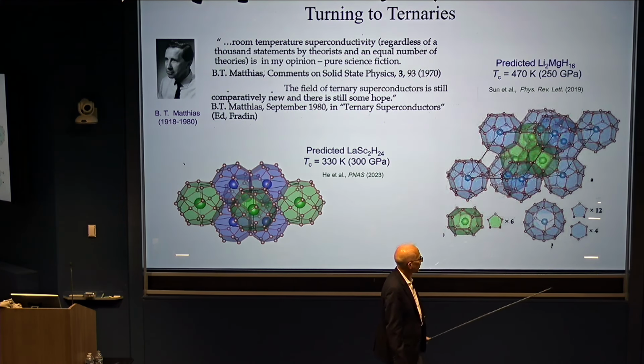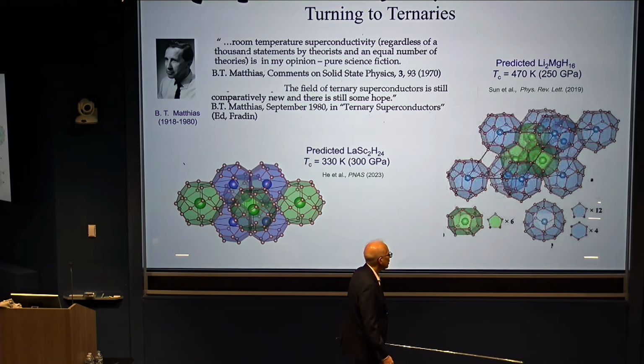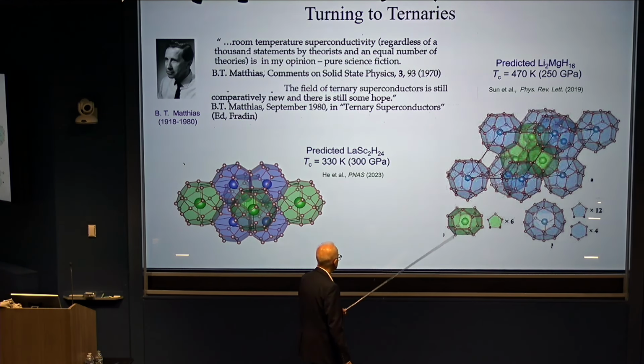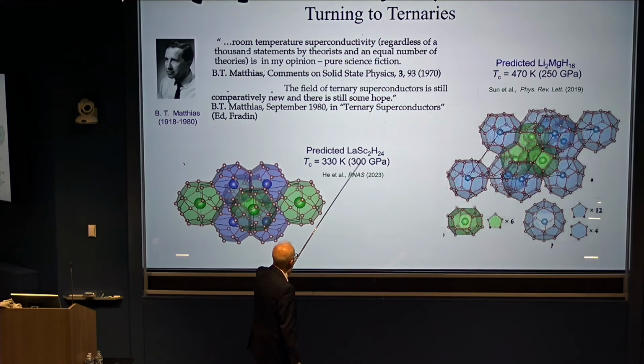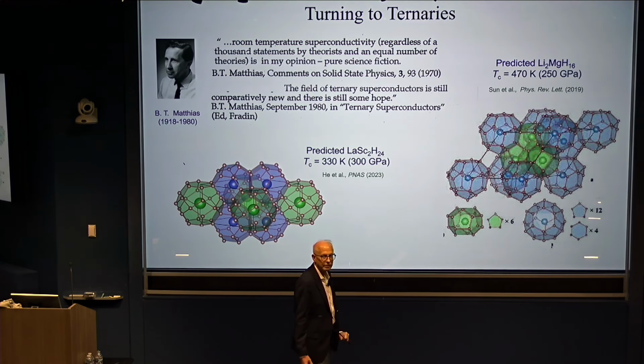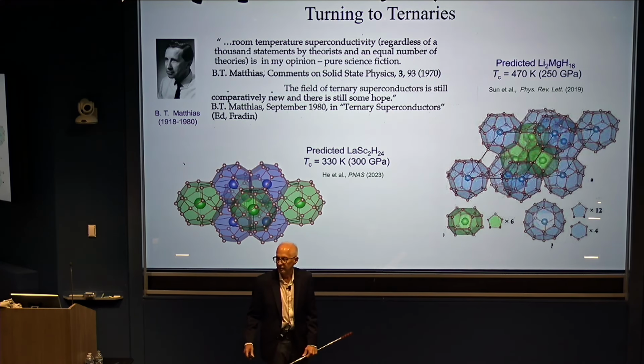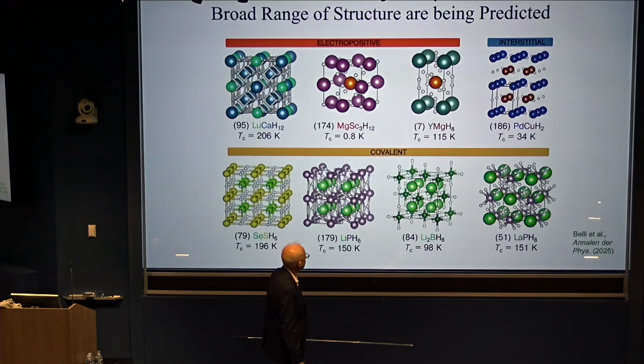So obviously an important one to make. It's actually metastable under those conditions, but it's an important one, and we're still chasing it to a certain degree. Here's another study that I happen to be involved with. If you just add some scandium to lanthanum and look for the lowest energy structures, you find some pretty interesting phases, this one with a TC above room temperature as well.